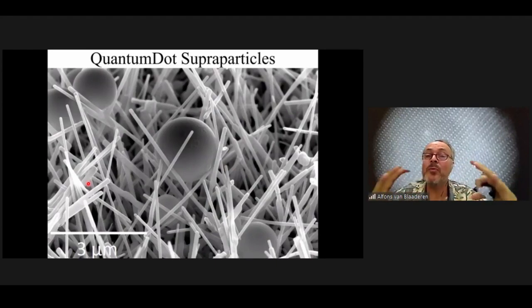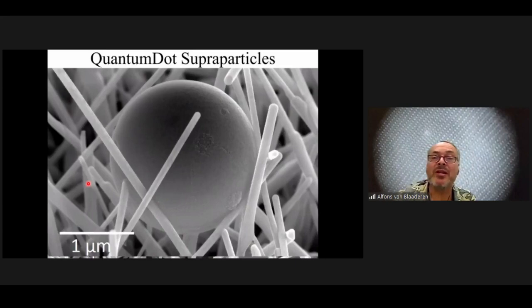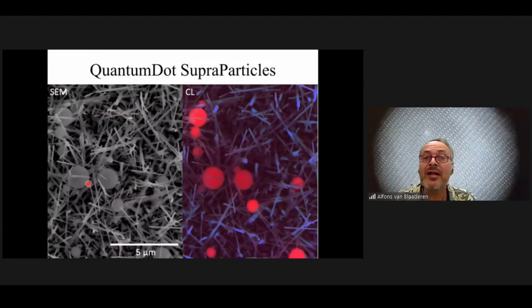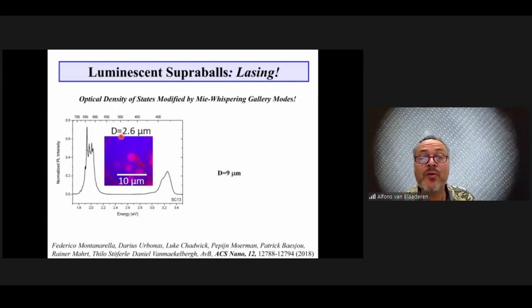However, if we make these superparticles not a few hundred nanometers, which is interesting for televisions, but a few micrometers, then the optical density of states starts to be modulated quite strongly, because we get Mie whispering gallery modes of these nanoparticles, and that modifies their emission. So we see here some zinc oxide rods which can also be excited with UV light, and in this cathode ray luminescence we see beautiful red luminescence of the superparticles excited by the UV-excitable zinc oxides. So what we get if we have superparticles of a few microns in size is that in the red emission, you start to see individual modes